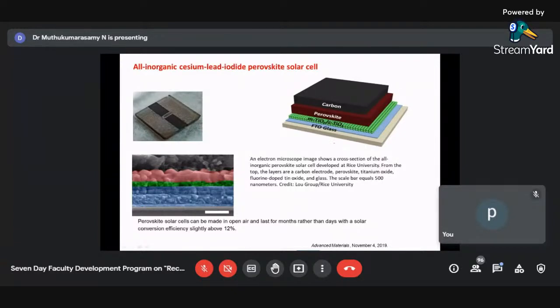So you can see here you have your FTO glass over which you have MTiO2. MTiO2 means mesoporous TiO2, then compact dense TiO2, which is for effectively scavenging the electrons. They have a compact TiO2, then mesoporous TiO2, then a perovskite material, then carbon material. You can see here they have not used any organic material, and they have achieved an efficiency of 12%.